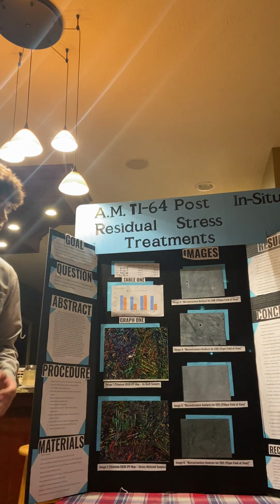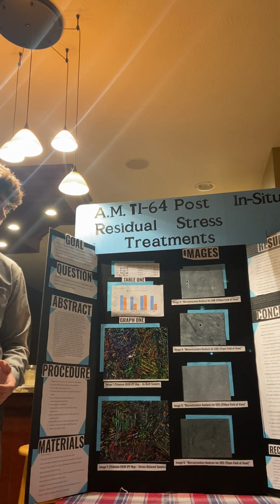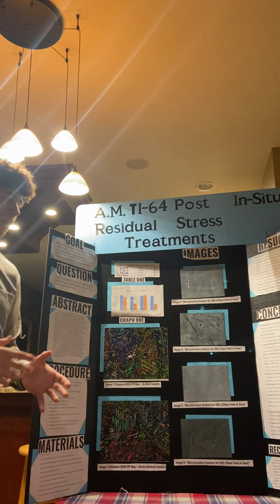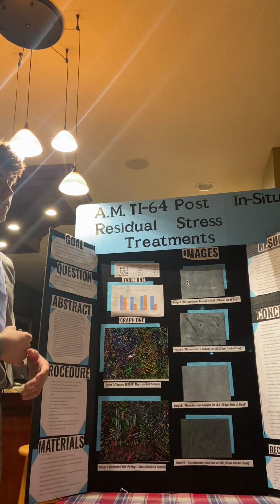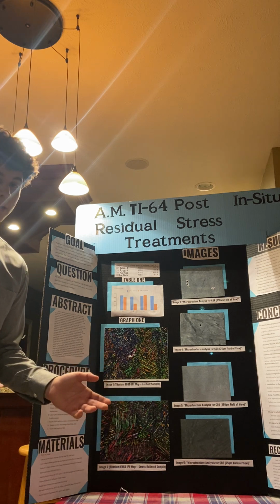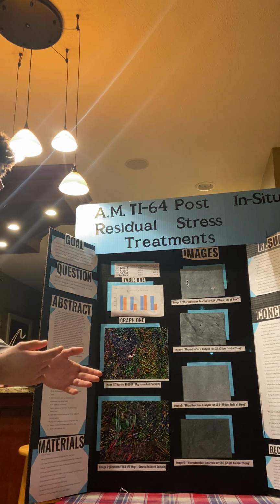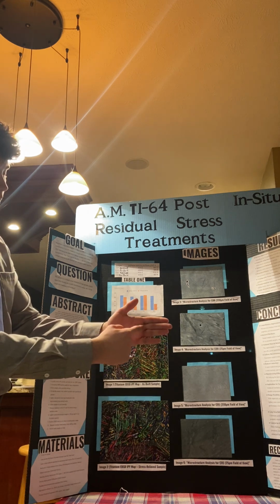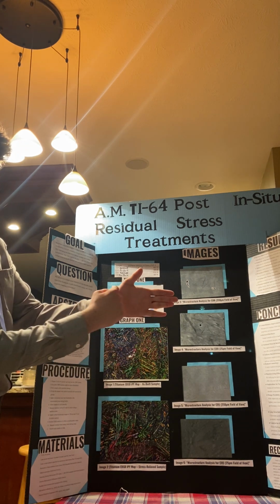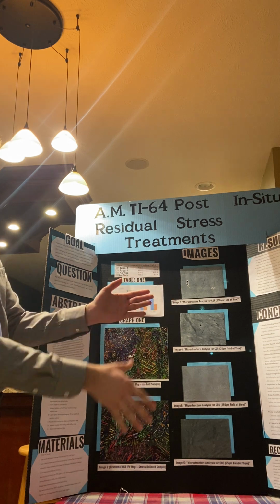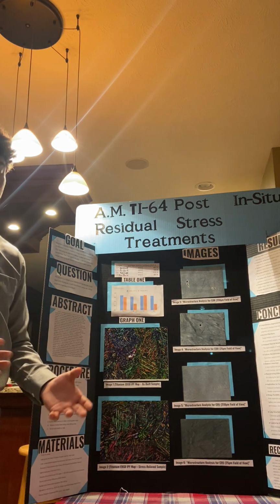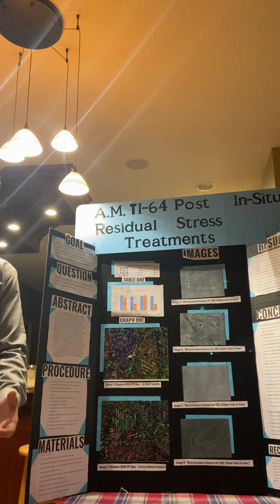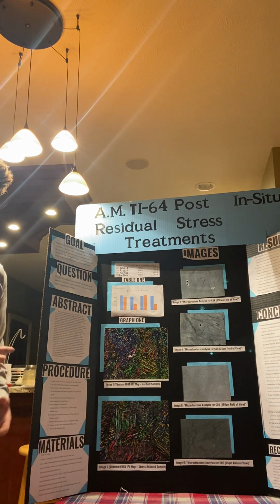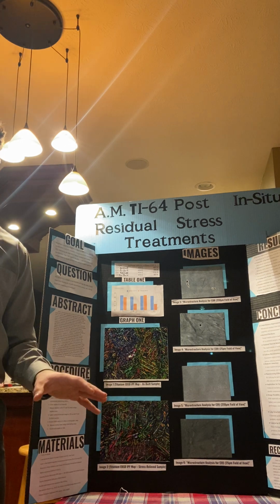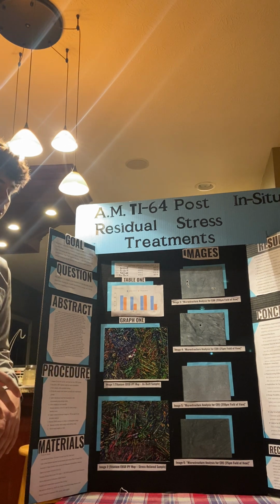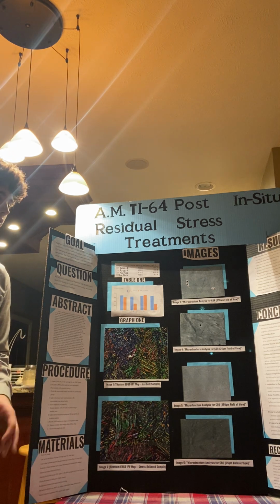And yeah, so for recommendations, if I were to do this again, I would fine tune the laser to find the exact pattern of the treatment that would be best. With this one, I chose 16 for the pattern. It's going to go over this, this is 1, then that's 2, and so it does 16 times. I chose this because I wanted to choose one in the middle. Too high would mean it might deform the metal and have too many effects on it, which would overall decrease the hardness and microstructure. And I wouldn't do too low or do nothing to the metal. So 16 was a nice number there.